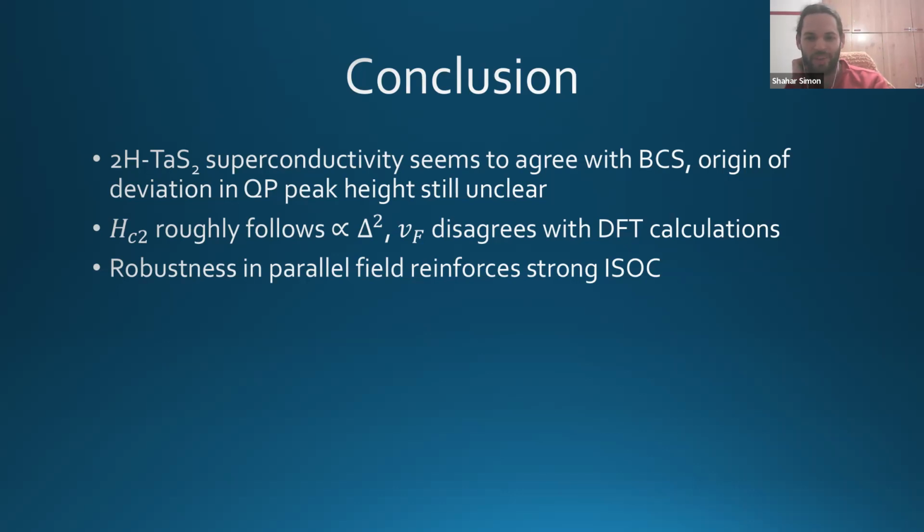It's funny because it's not exactly physics what I'm describing now, but when I look back on my calendar and I see when I finished fabricating a device and when I started measuring it, you can clearly see that if you don't immediately throw your sample from fab into your cryostat, you start losing height in your quasi-particle peaks.